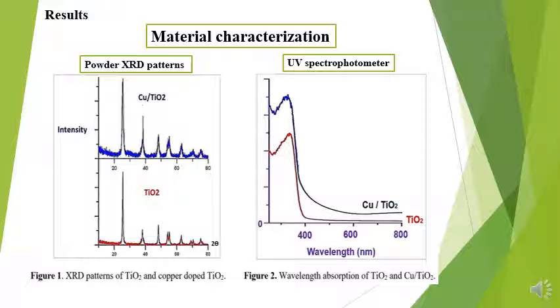We can notice a redshift in the absorption peak between titanium dioxide and copper titanium dioxide, and this redshift could be attributed to the charge transfer transition between the semiconductor and the metal. In the UV wavelength region between 200 and 400 nanometers, the relative intensities show in a decreasing order for copper titanium dioxide and titanium dioxide. In the visible wavelength region between 400 and 800 nanometers, we can notice that the absorbance is considerably enhanced for copper titanium dioxide.